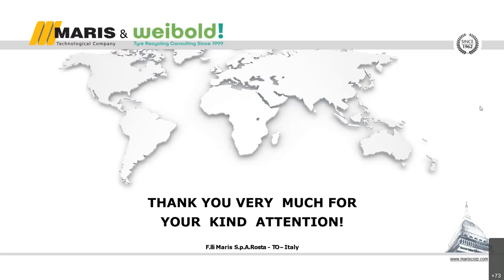Luciano, one comment. We have received one question on this topic. They are asking 1 centimeter or 1 millimeter, to clarify this. Yes. Well, in terms of powder, we start from 0.6, 0.8 millimeter until 1.2, 1.3 millimeter. These are the minimum that we are working with. In terms of highest particle size, and I'm again talking about millimeter and not centimeter, we are talking between 5 and 10 millimeters. Then it is not a matter of having 12 millimeter or 13. It's flexible. What is important is that what is introduced into the machine, like Marco said, has some kind of homogeneity. So a mix of powder and particles is not well accepted by the process, it should be either powder or particles. But again, we are talking about millimeters.